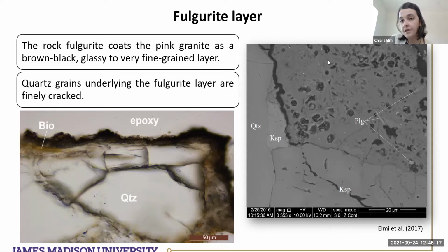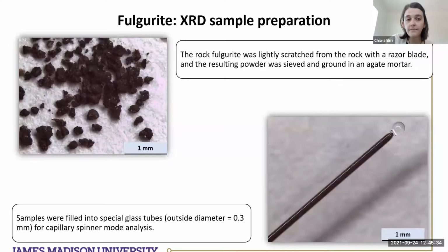Based on this glass matrix, but in particular the minerals that were embedded and frozen mostly into the glass, I was able to reconstruct the conditions when the lightning struck there. I developed a new protocol for the X-ray diffraction to study this kind of material, because there is not a lot of glass on the top of that. It is a few microns of sample, so it's not enough for the usual stage for X-ray diffraction.